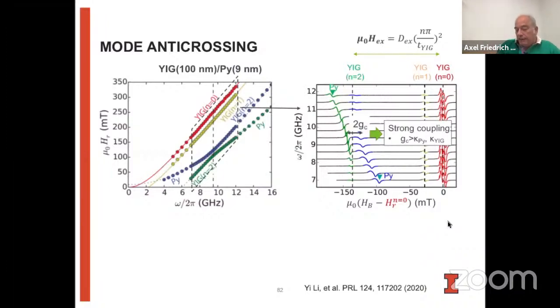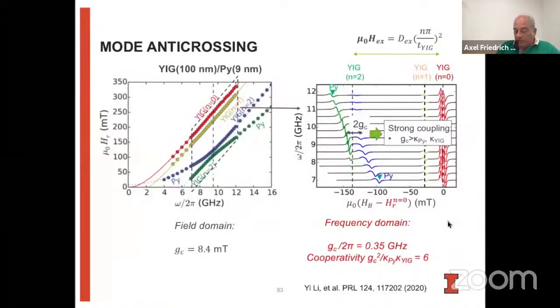We can, as before, calculate the coupling constant and compare it to the dephasing rate of the permalloy and the yttrium iron garnet on its own. The dephasing rates we can determine being far away from the coupling, and the coupling we get from the coupling mode itself. When we do this, we get a cooperativity of 6. It's an order of magnitude less than what I showed you earlier, but it's still quite significant. So in the field domain, this corresponds to a mode splitting of about 8.5 millitesla.